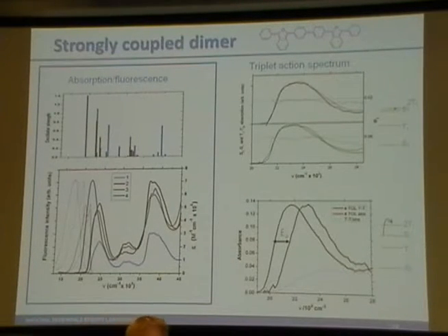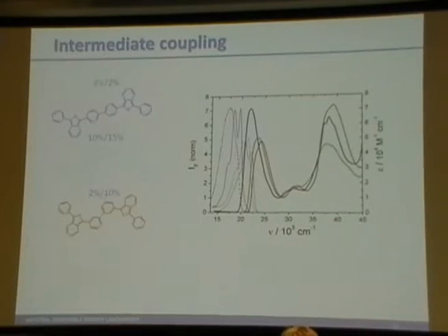That's bringing us closer to the first case I mentioned with smaller exchange splitting. And the yields in this case are quite small. They're just a few percent. So it suggests that even though you put in enough energy up here for singlet fission to occur, the relaxation processes that bring it back to S1 are easily outcompeting singlet fission. So that's not necessarily the best case.